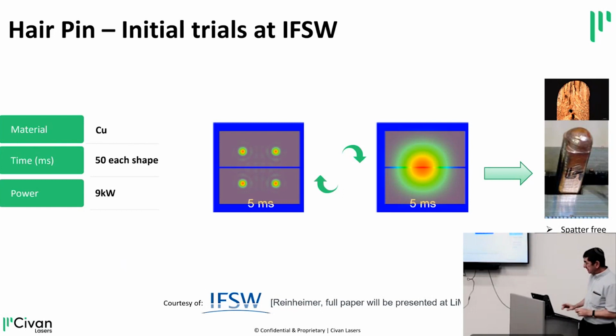The problem is that they are not perfectly aligned. There's always a gap between them. Sometimes there's height difference. Sometimes their shape is not perfect. And if you just come with a laser from the top, some of the energy penetrates through the hole between them, and damages the isolating layer between them. So first of all, you waste a lot of energy, but second, you do damage with the laser inside.